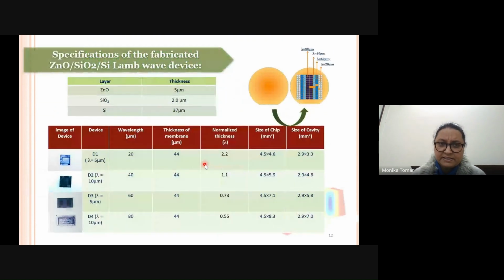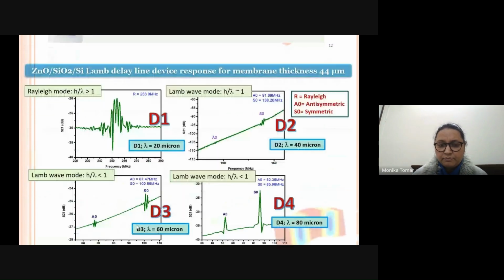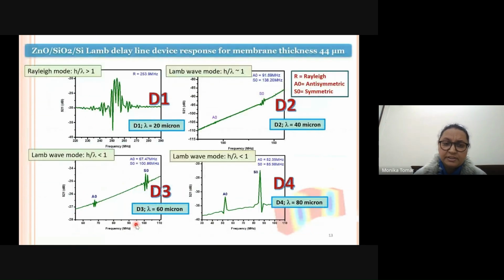So these are the typical specifications of the fabricated zinc oxide, silicon dioxide, silicon Lamb wave device. The thickness of different layers is kept as: zinc oxide is 5 micrometer, silicon dioxide is 2 micrometer, and silicon membrane is kept at 37 micron. So we have the different devices that we fabricated, D1, D2, D3, D4, which have different acoustic wavelengths like 20 micrometer, 40 micrometer, 60 micrometer, and 80 micrometer. Based on that, the devices were fabricated, and these are the responses of the 4 devices.